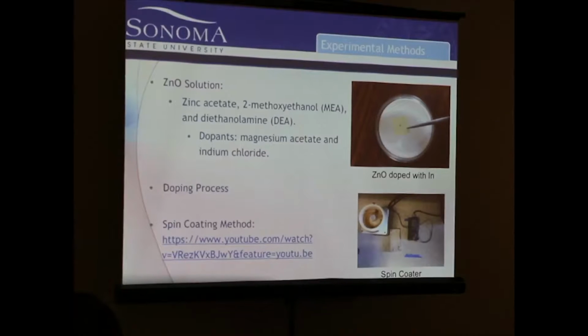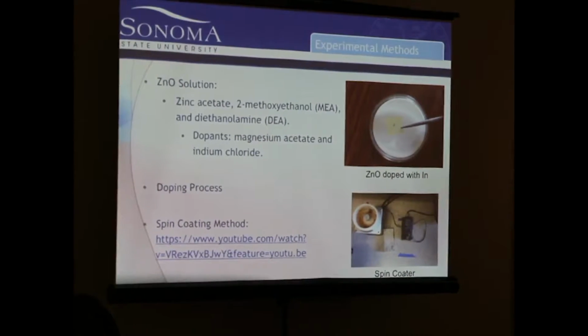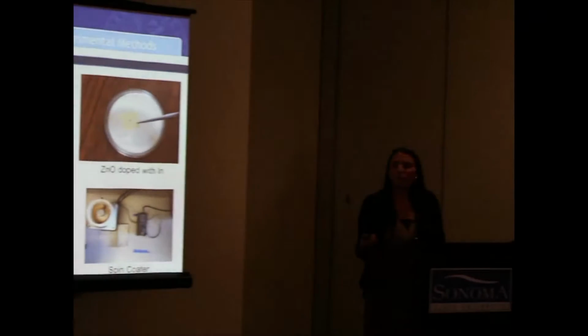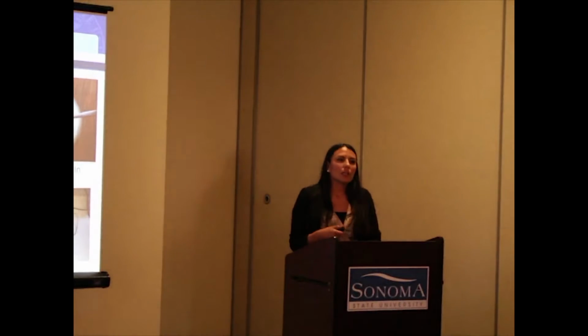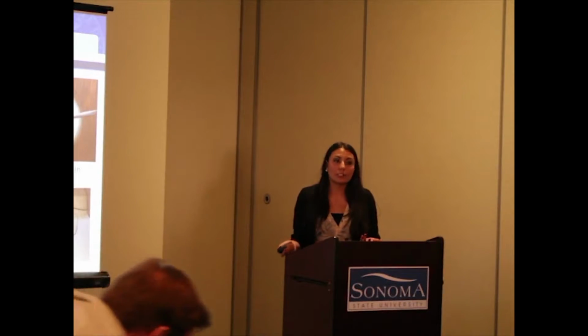So the experimental methods that we thought we should try is using zinc oxide as a solution. What we have is zinc acetate and then MEA and DEA. The MEA and DEA really are a sticky solution, so if you were to feel it, it's kind of thick and sticky. That really helps us bind our zinc oxide to the substrate, which is here, the glass. And I use dopants, and dopants are just when you add very low concentrations of different materials to really check how it changes the structure.